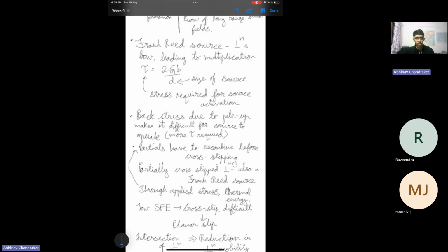Now we had already looked at bowing of dislocation, the stress required for a dislocation to bow. So we will now take that forward through one phenomenon which involves the bowing of dislocations, and that is multiplication of dislocations by a Frank Read source. Usually this source is some obstacle, and when a dislocation goes through, the outcome at the end is that it will form a new dislocation loop, which can keep moving forward without any impediment.